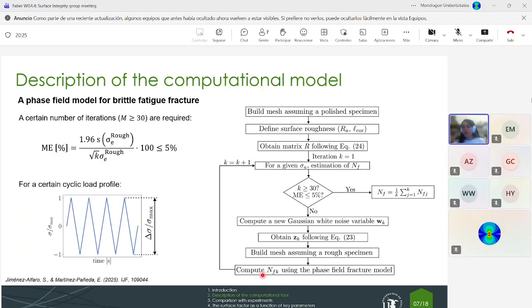And then we use the phase field model to determine the number of cycles to failure. We iterate this procedure until we fulfill two different conditions. The first one is that we have at least a sample size of 30. This is because a minimum sample size of 30 gives us a Gaussian distribution. And the second condition is that the relative margin of error is less than 5%. So if we fulfill these two conditions, then we are finished, and the number of cycles to failure is the mean of the distribution that we have.